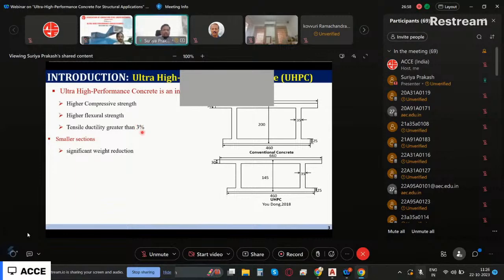But usually concrete is going to fail at a strain of about 0.003. If you convert to percentage, it is going to be 0.3%. So you can see here it is increasing multiple times. Then because I'm having higher compressive strength, I get higher tensile strength.